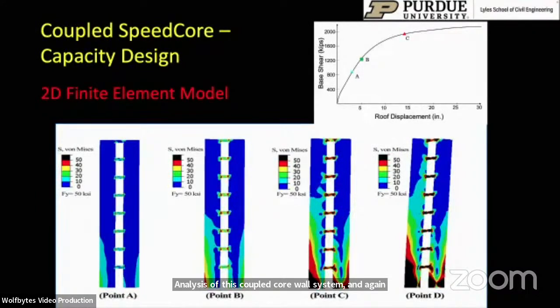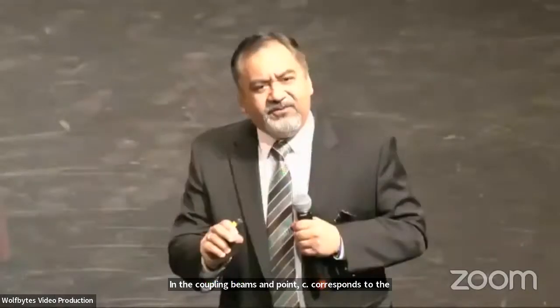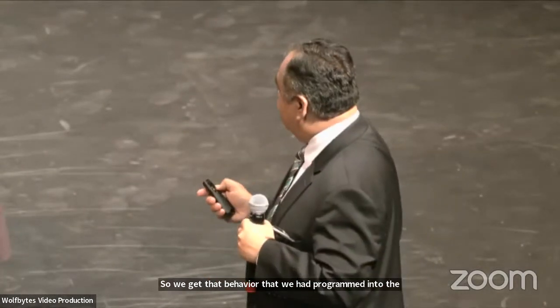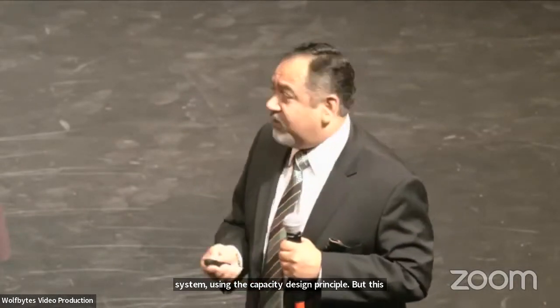Point B corresponds to the spread of plasticity along the height of the structure in the coupling beams. And point C corresponds to the formation of plastic hinges at the base of the walls. So we get that behavior that we had programmed into the system using the capacity design principle. But this is just static pushover behavior.